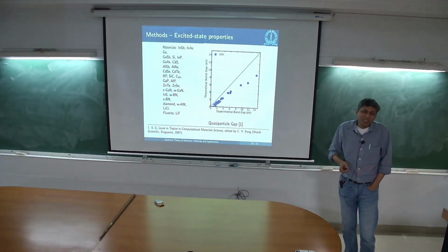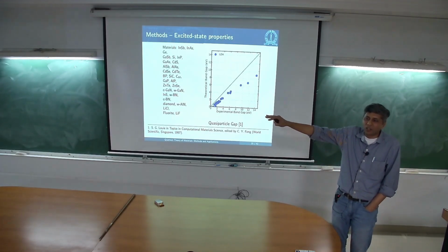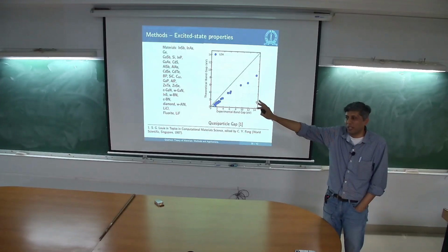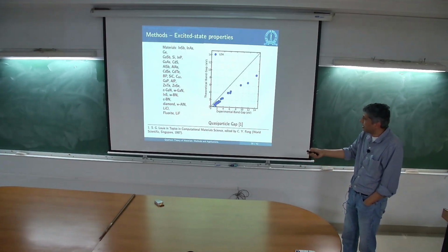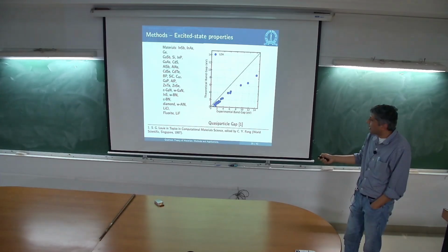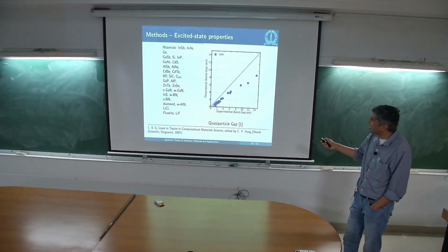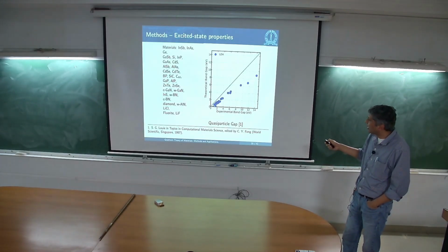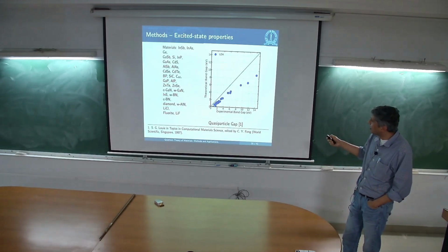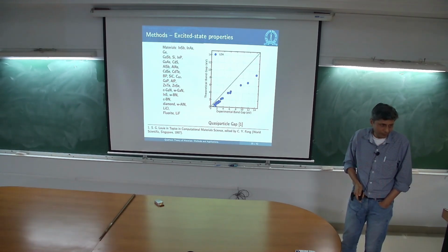Imagine you said, you know what, this is all too complicated. Let's not do all of this. You already had a one electron problem. It gave me eigenvalues. Maybe that's good enough. If you take a large number of materials, and you plot the experimental band gap versus the theoretical band gap, and you do this within the local density approximation, this Kohn-Sham thing that I told you, these are the points you would get. And you would see that this is where it would be if experiment were agreeing with theory. Clearly, this is not agreeing very well, right?